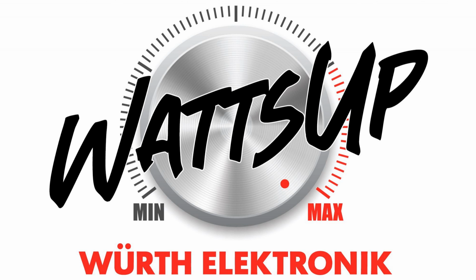Ferrite beads are made to dissipate heat. However, the more it dissipates, the higher the operating temperature reached. We can see a typical temperature profile of a chip bead with a Curie temperature above 180 degrees Celsius, and this is where the measurement is carried out from negative 55 degrees Celsius to 160 degrees Celsius. In our example, we can see that the higher the temperature of the component, the more the impedance is shifted down, becoming more saturated. The optimal operating temperature would be to stay as close to the ambient temperature, around 20 degrees Celsius to 25 degrees Celsius.